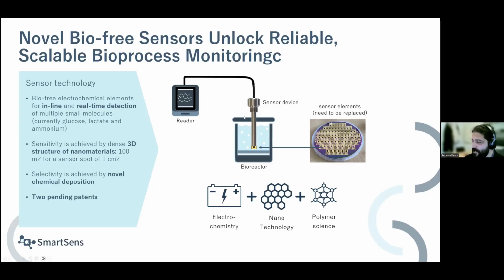So the sensor device, you can see it here, we have produced it, and this integrates sensor elements. The sensor elements integrate with the sensor device, and need to be replaced after each reactor run, and you can get the signal out. The way it works is based on amperometry. When we apply voltage, these small molecules or analytes interact with the working electrodes, and they undergo reductions or oxidations. For example, if they are reduced, they also release electrons, and that electron can be amplified, and then the signal can be correlated with the concentration of those small analytes in the solution.